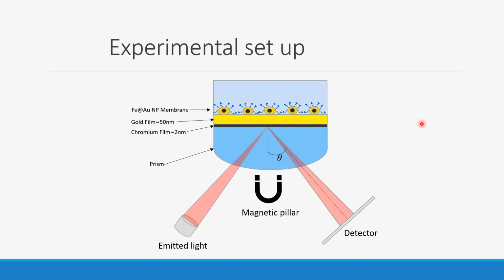Once the functionalized nanoparticles were introduced into this sensing cell, these nanoparticles were attracted by this magnetic pillar, forming this sensing membrane at the surface of a gold film, followed by a chromium film. These films were excited with incident light that was focused with the prism under the Kretschmann configuration, achieving the resonant condition by attenuating total reflection. And the prism was coated with these layers of metal films.